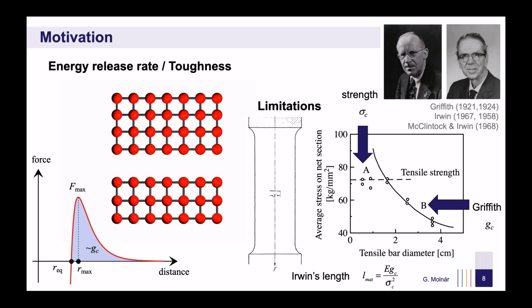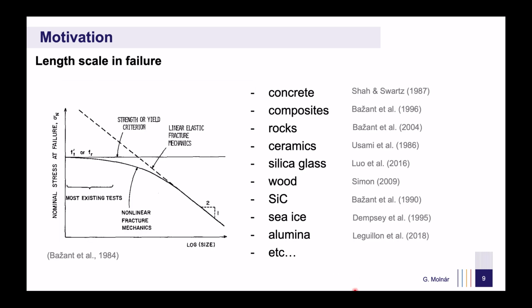He showed that the simplest material length can be defined using E, Young's modulus, Gc, the toughness proposed by Griffith, and sigma c, the material's tensile strength. Interestingly, while Irwin is widely recognized for developing the stress intensity factor, this particular finding was overlooked for decades. Since Bažant's revival of this concept, the size effect has been experimentally confirmed across a wide range of materials, from silica and ceramics to ice sheets.